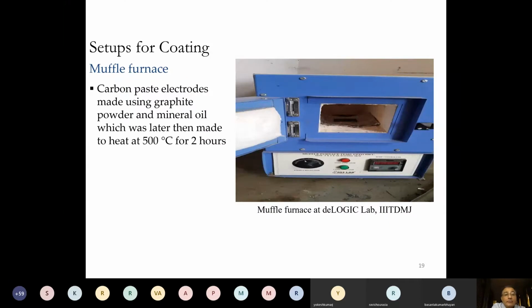Then we also try to put the carbon paste electrodes, which were made using graphite powder and mineral oil, on the ceramics to generate the first spark. If anybody is having any confusion, let me make it very clear that if you have a pure ceramic material, you cannot generate the spark in it, and spark is necessary for the EDM process, because without spark the machining will not start.